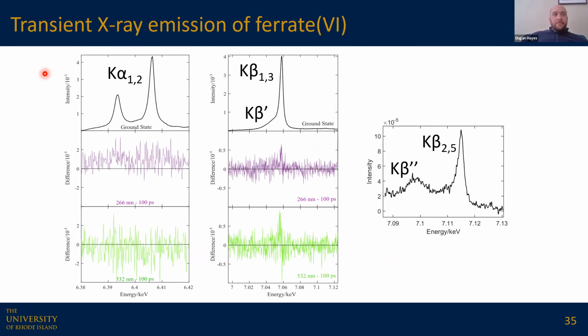So aside from the fact that our transient K alpha signal is essentially 0, we don't see any difference here. And our transient signal in the K beta is very, very weak. This is exciting in its own right because it occurred to us much later that this is, to our knowledge, the first example of even a steady state X-ray emission characterization of an iron(VI) compound. So we think that's pretty exciting and pretty unique in its own regard. But right, we don't see any difference in the K alpha following either UV or visible excitation.